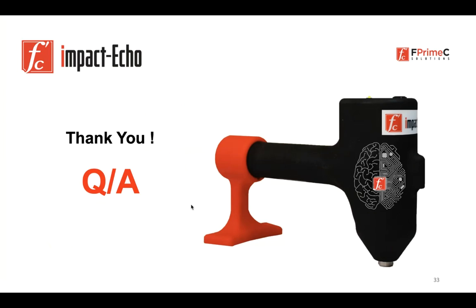Yeah, thank you. And is it feasible to carry out the impact echo test on masonry structures like arches? If masonry means brick and paste, I don't really recommend doing the test on those structural members. They are not homogeneous, and the test area is a combination of different interfaces between the cement paste and the brick. But if the structural member is masonry with no other things like brick, you can use your impact echo device.